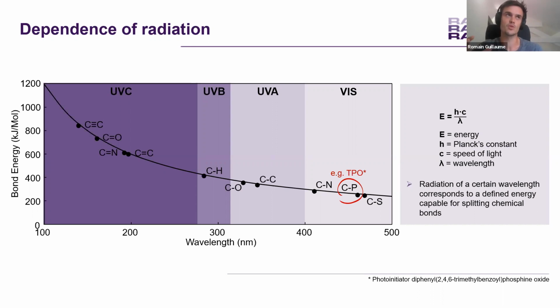So that's also a reason why sometimes we can't cure something with LED, which are emitting mainly in the UVA. So if you have a triple bond which requires a wavelength of 150 nanometers in order to be broken, you can't do that with only UVA. So that's why we need to take into consideration the formulation of the coating when we need to select the lamp and the technology of the lamp behind it in order to match the wavelength emission and the wavelength sensitivity of our coating.